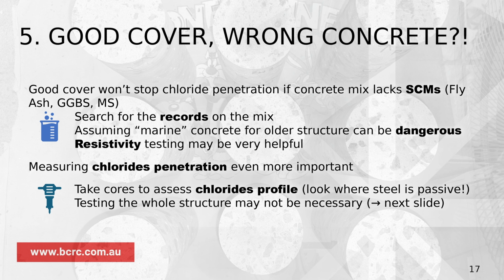I did see a number of structures which provided a good cover. However, chlorides getting in with no problem in fairly short time, I would say about 30-40 years. So search for the records of the mix. It's typically written on the drawings. If you don't have drawings, just assuming that because the structure in marine environment is built of marine concrete, could be quite dangerous. I'd say the easy way to test your concrete is with resistivity testing.